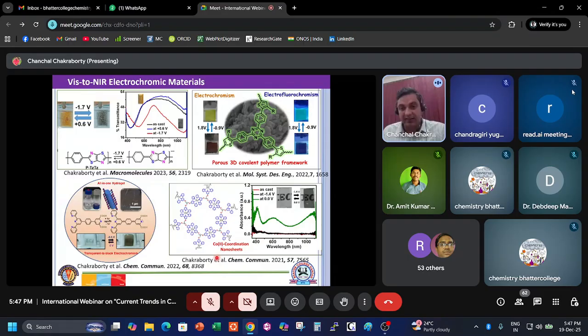So 68% blocking. For that, we went to the metallo-supramolecular polymer structure. Our strategy was that we can use cobalt as the metal, so that the reducible cobalt(II) center can produce cobalt(I). We first synthesized an aldehyde-containing terpyridine, and then by a condensation reaction we generated this ligand, the thiazole and terpyridine. So this is a ditopic ligand. When we charged it with cobalt acetate, we got the polymer. And one important thing over here is the NMR, so we produced stepwise NMR.